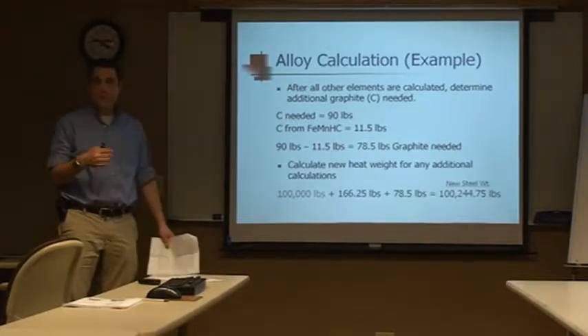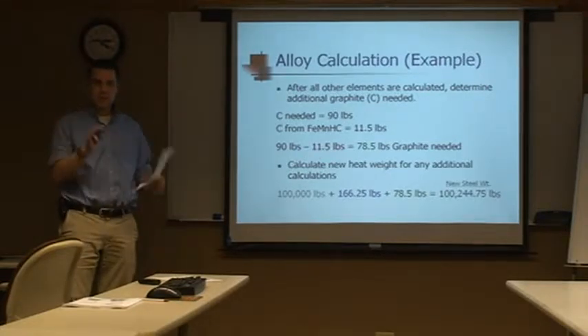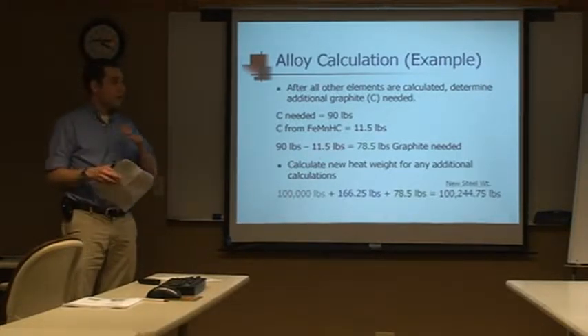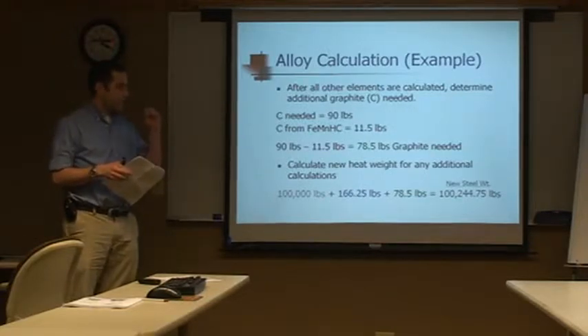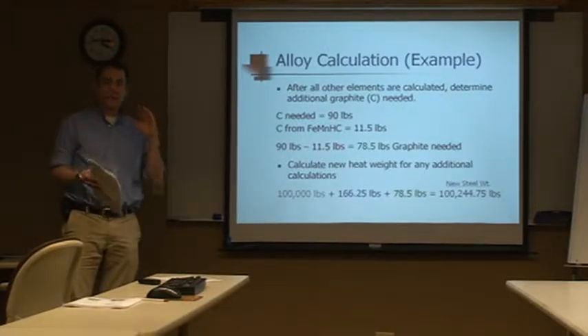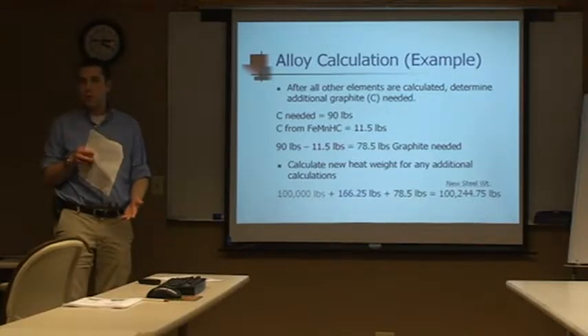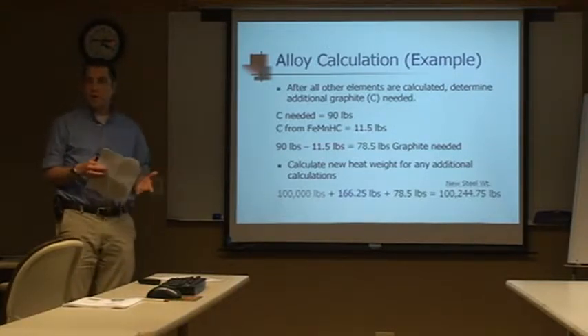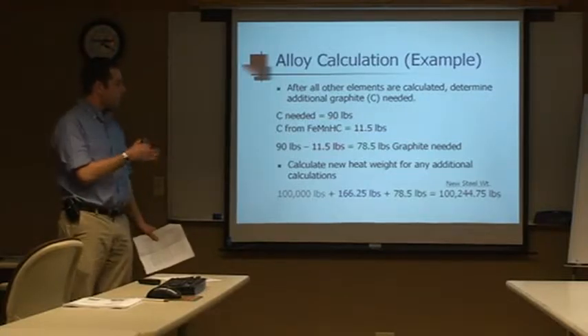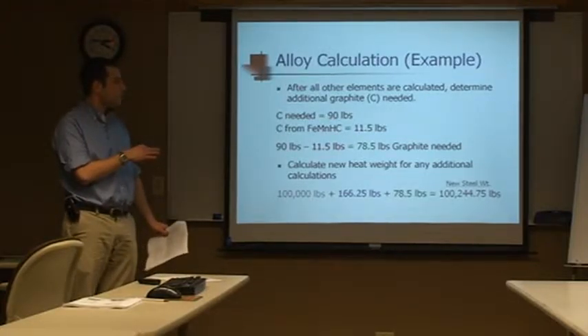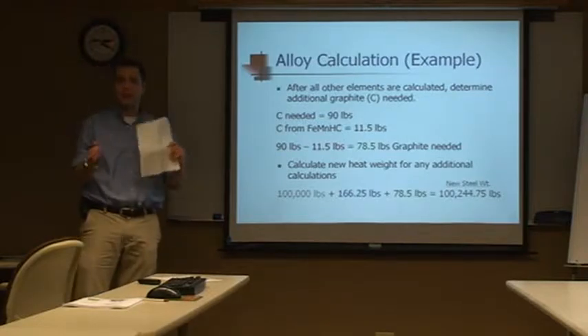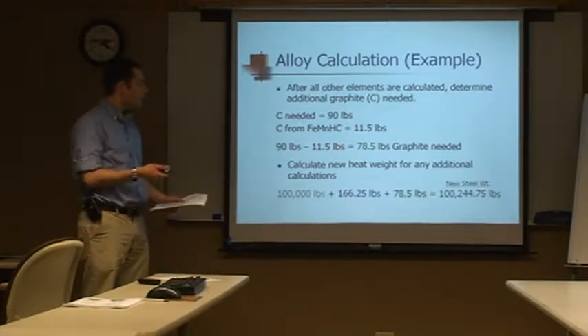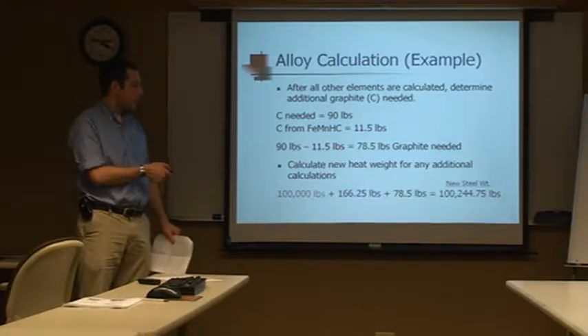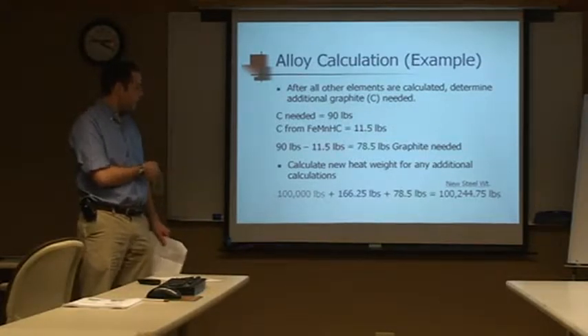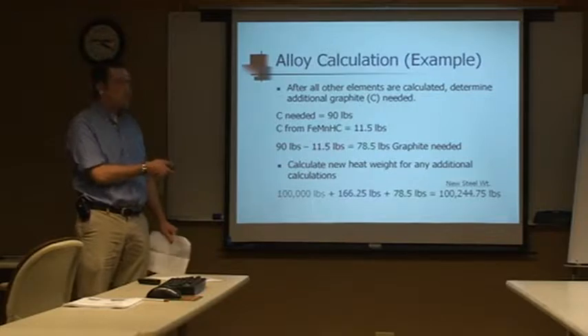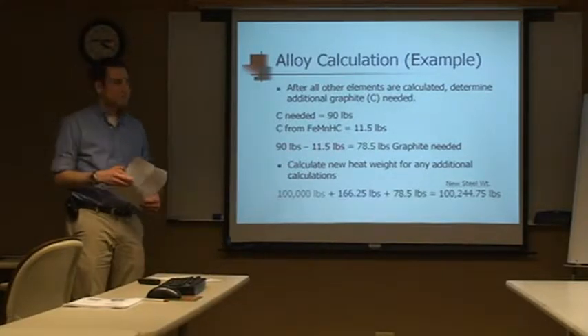Now ideally, at this point, everything's within range and we can just go forward with the steelmaking process. But we're going to take another chemistry sample and just see where we're at, because sometimes you don't get the recoveries you're looking for, or the heat weight might be a little off. So we try and be as efficient as possible with the alloy calculation to make sure we don't have to go back and tweak very much. But if we do, we need to make sure we have the new steel weight calculated, which is the original steel weight plus all the adds that we figured out.